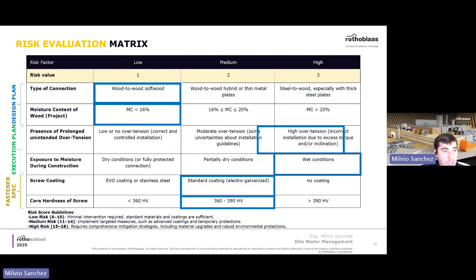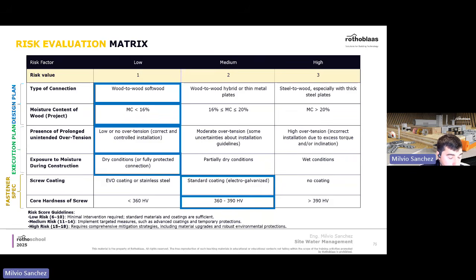But by simply installing the screws in the correct way, following manufacturer recommendations, and protecting the CLT panels with membranes, temporary membranes, taping the end grains, you can reduce this wet surface to dry. So now in this case, if you do the sum again, you're going to fall in a low risk condition. So you can play with this matrix and develop your own as well. This is just a suggestion, but it is interesting and important to say that not every single connection is high risk, and not every single connection demands the same level of moisture protection.